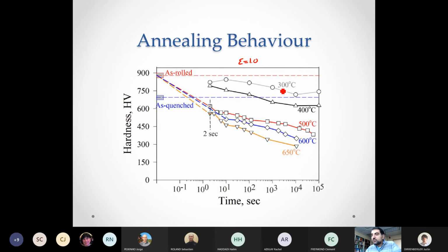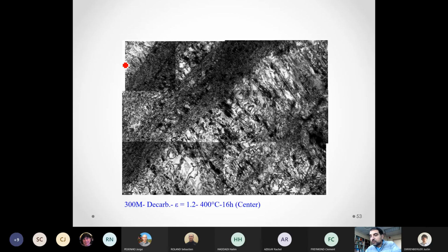At low temperatures, 300 and 400, the main event is recovery. Once we go above that, we begin to see a lot of recrystallization in the samples. And I'm just showing here an example of one of the recovered structures. You can see this area here is the deformation band. It's very easy to see. That's the shear band or the deformation band with very high dislocation density and very small cell structure.